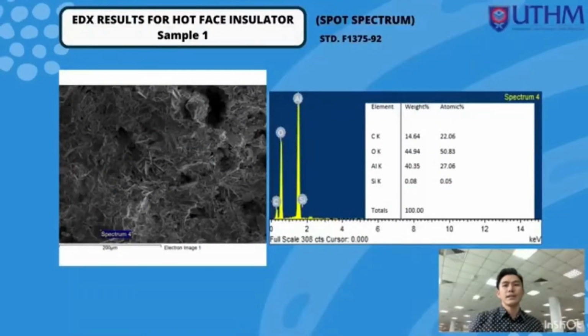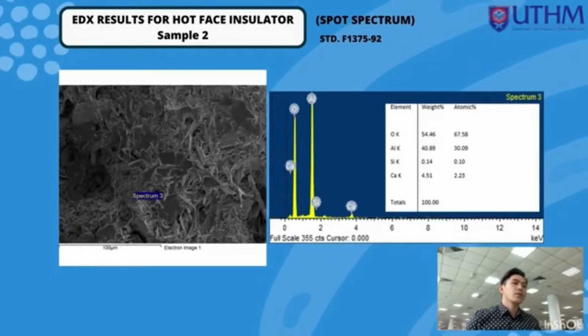And we are now at the EDX result for the hot face insulator, which we can see from the slide is the first sample. We did it with the spot spectrum. For the surface at 250 magnification, we found the elements carbon, oxygen, aluminum, and also silica. So the highest weight percentage found among the elements is oxygen. Then for the second sample of the hot face insulator, which we did with the spot spectrum, we found the elements oxygen, aluminum, silica, and also calcium. So the highest weight percentage is taken by oxygen.